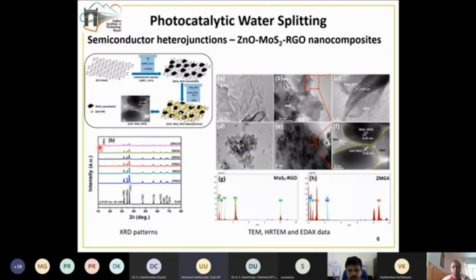One reason is the peaks of zinc oxide dominate the X-ray diffraction pattern. And the second reason is the MoS2 is found in very, very low concentration. It is in low concentration and also the peaks don't dominate. That's the reason we are unable to see the MoS2 or RGO in this case, but we are able to notice it using another technique.